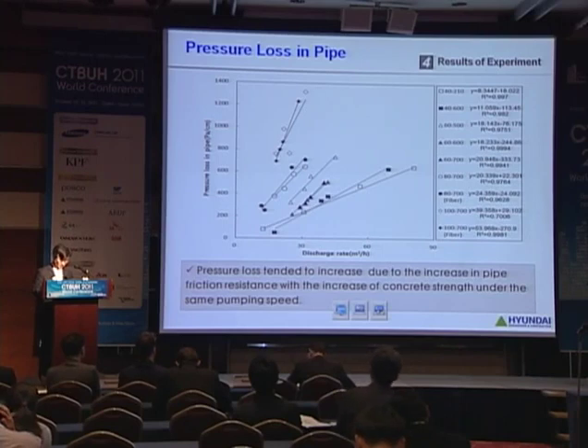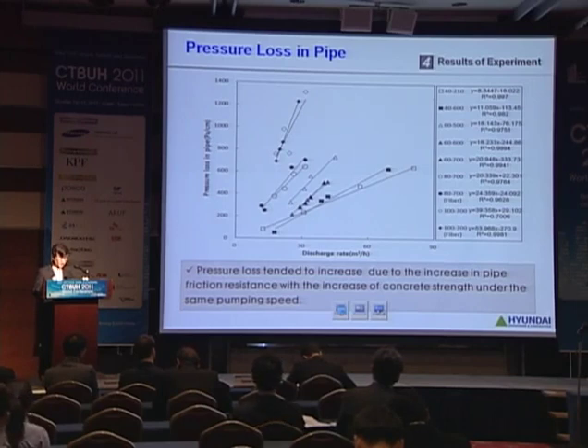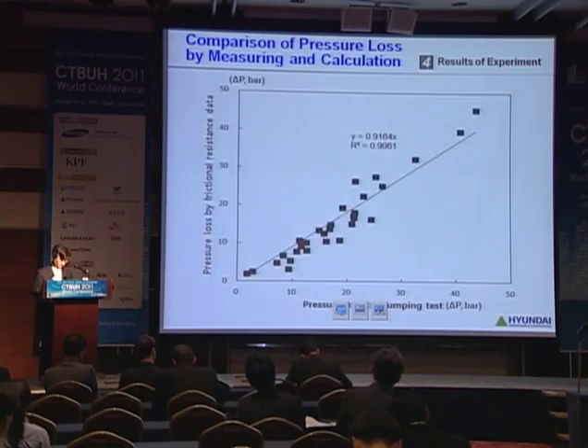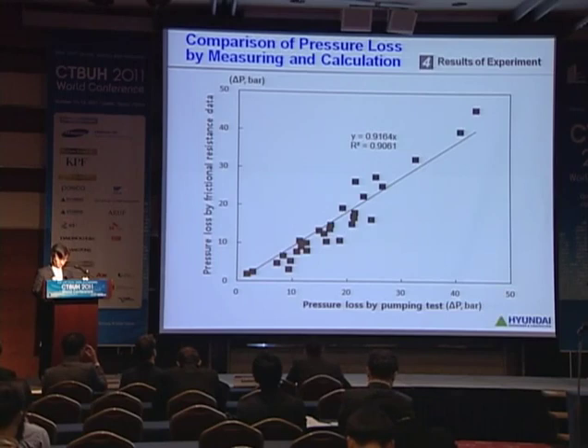Pressure loss in pipe tended to increase due to the increase of friction resistance with the increase of concrete strength under the same pumping speed. In this graph, the x-axis is discharge rate as pumping speed, and the y-axis is pressure loss in pipe. This figure shows the relation between pressure loss by pumping test and pressure loss by calculation of friction resistance coefficient. The result shows high regression.